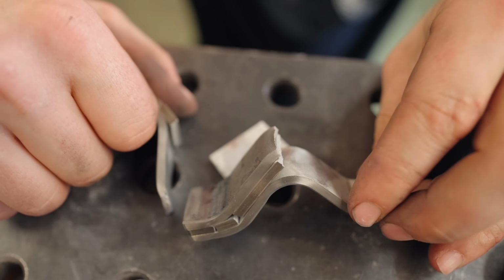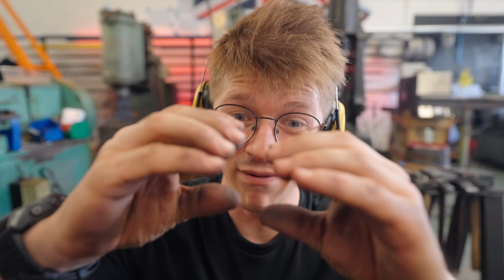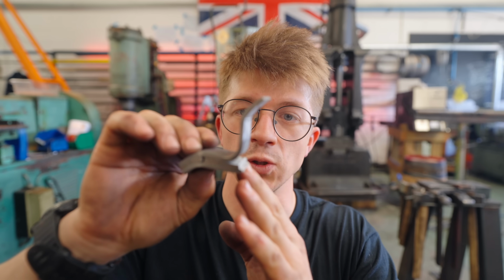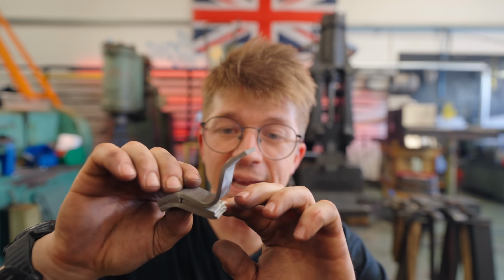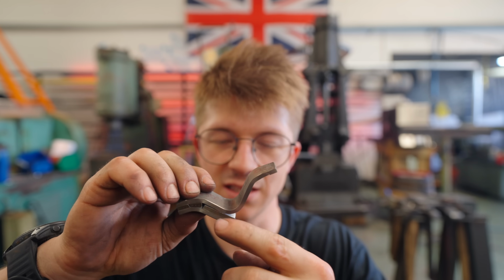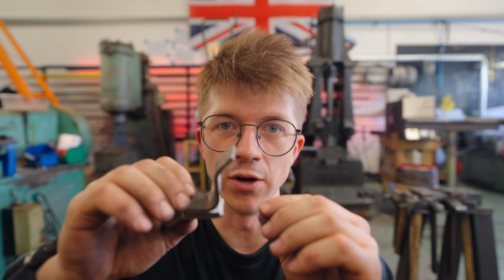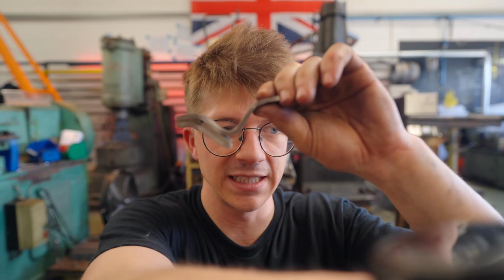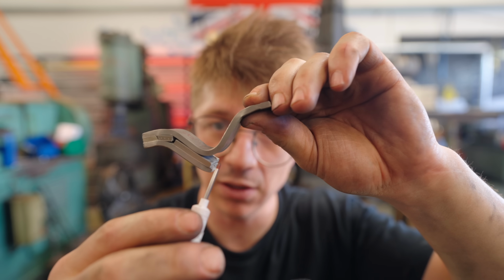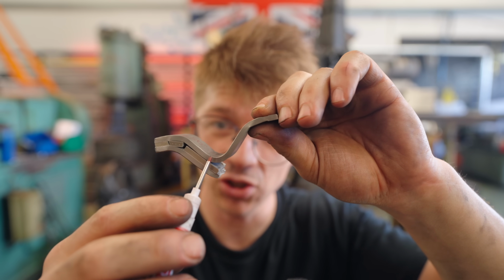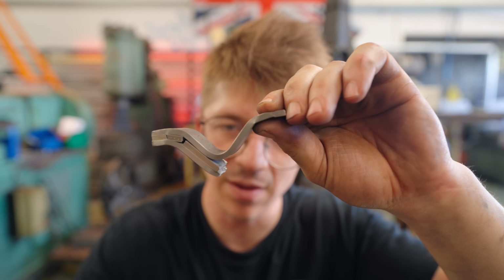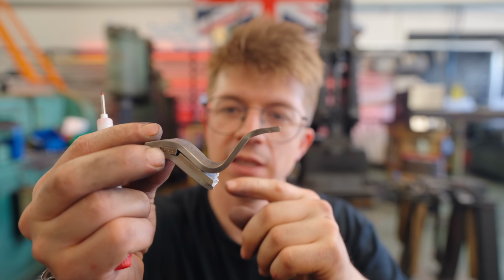I might have liked the steel to stay stuck to the titanium a little bit more and maybe force the titanium to break where the steel broke. So instead of the steel breaking and then it peeling as the titanium then takes the bend, I almost would have preferred the steel broke, but the bonds between the steel and the titanium, just either side of where the steel break, would have been so tight that it would have made a stress concentration to the titanium and broken the titanium there. Obviously, our bond between the steel and titanium is not as strong as the steel itself. I think that's what you can deduce from it.